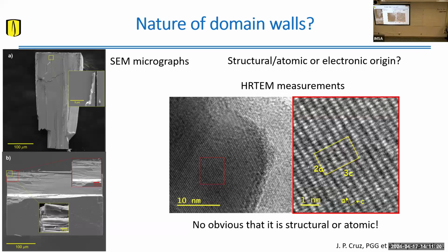And the assumption is that they appear macroscopic. It's not just an absolute finite density. Exactly. They have finite density and they are actually dynamical. So our claim is that all these transitions and changes that you see in the resistivity are not a consequence of a real phase transition. These are actually highly hysteretical. So these domain walls can easily move across, since an electronic defect will have more flexibility or a lower energy barrier to move than a real vacancy in the system. So they are highly movable.